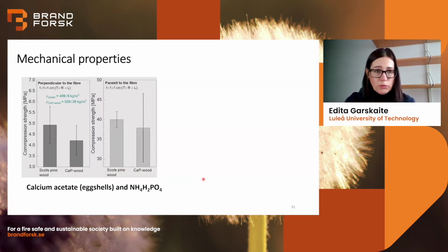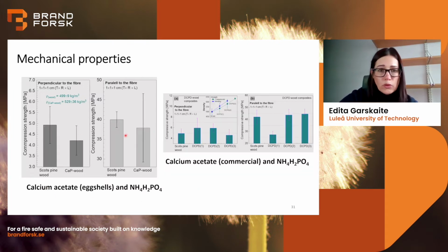We also measured mechanical properties, and they didn't show much difference compared with a reference wood. We got maybe even slightly reduced mechanical properties, but that can also be attributed to the not fully saturated matrix, and also the pH is different when we prepare these materials. We used a little bit more basic solution, and maybe that induces some more changes in the actual wood material.